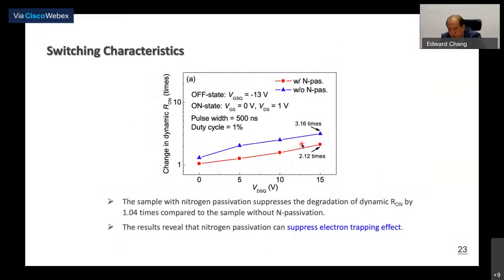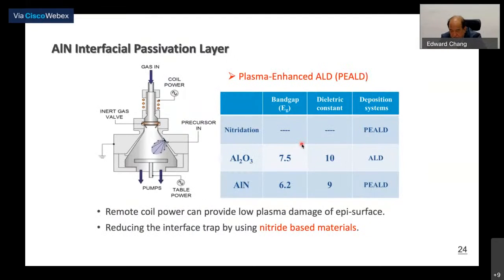And this also shows you the current collapse, okay. Once your surface is perfect, you don't have the charge trapping effect, then your current collapse will be reduced. This is compared with nitrogen passivation and without nitrogen passivation, okay. So you can see its improvement. And also the passivation is very important, okay, because with improper passivation, you can have current collapse, and you can use aluminum nitride by PEALD, or aluminum oxide by ALD, types of things, okay.